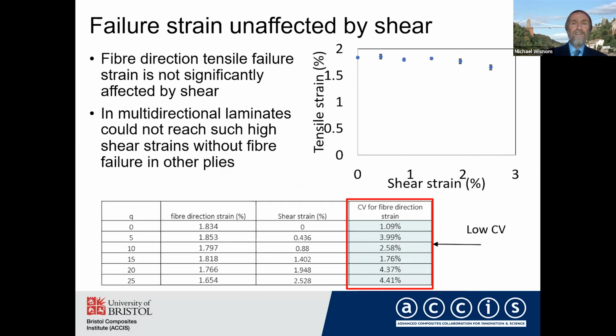And if you look at the failure strain, you find that actually there's hardly any difference. These results up here show that up to 2% shear strain, we have really hardly any effect on the tensile failure strain. And only at this very highest value here, we perhaps see a little bit of a reduction. So the fiber direction tensile failure strain seems to be not significantly affected by shear. And in a multi-directional laminate, you're never going to get up to as high a strain as this before you get failure in other plies. So these matrix-dominated stresses don't seem to have very much effect.